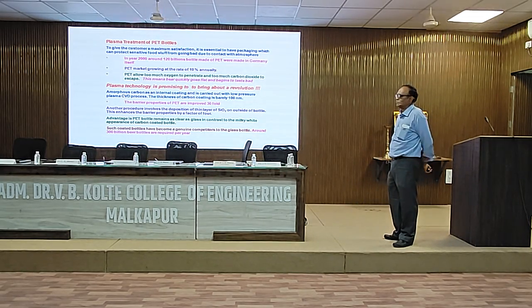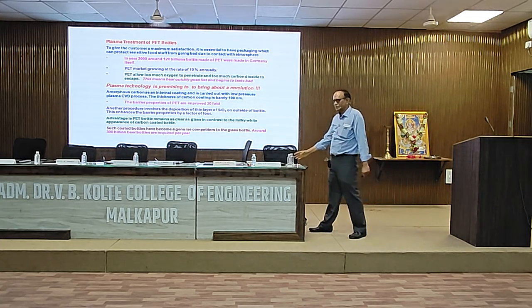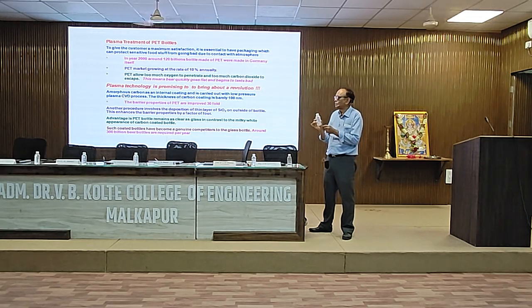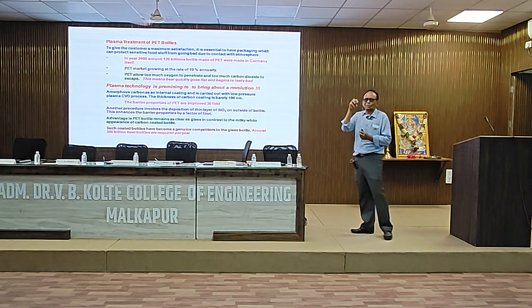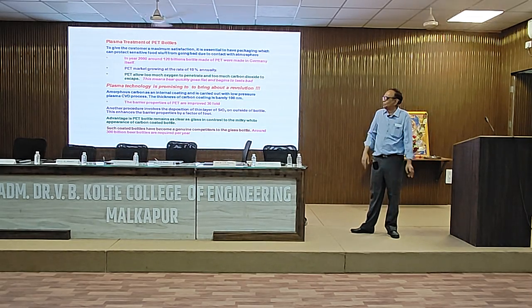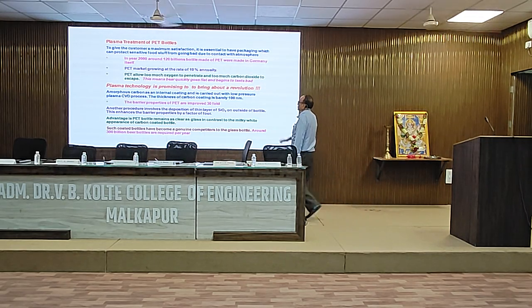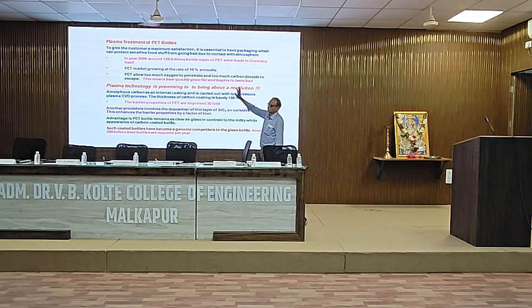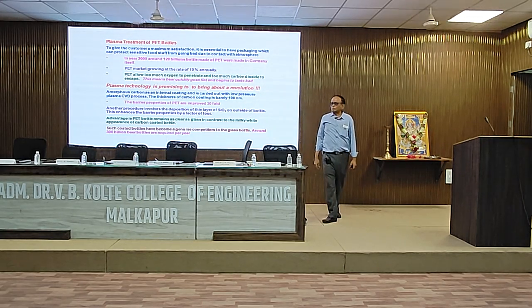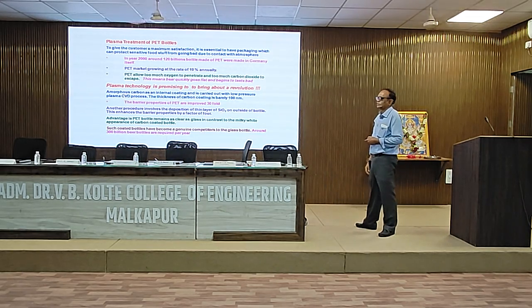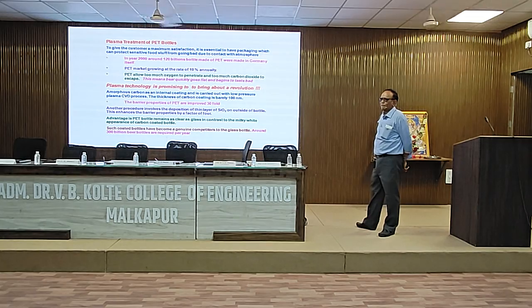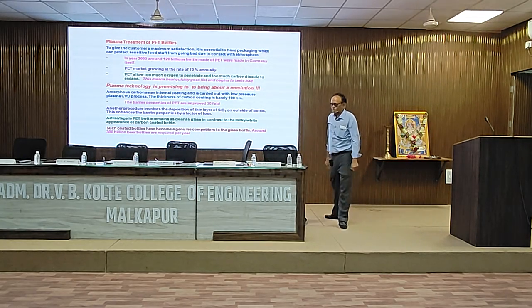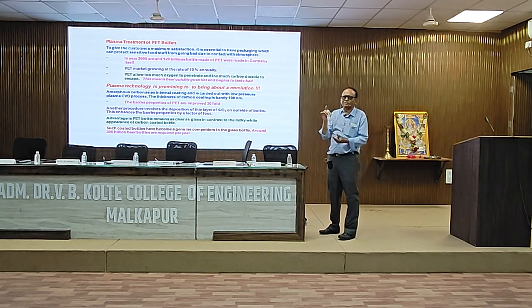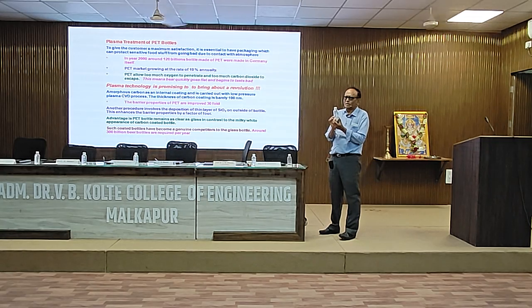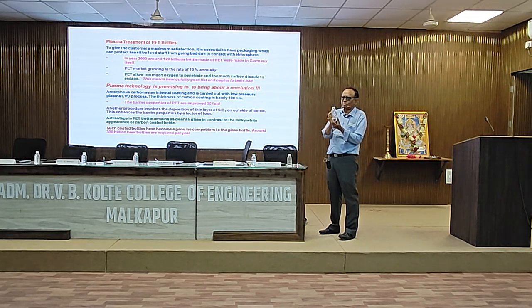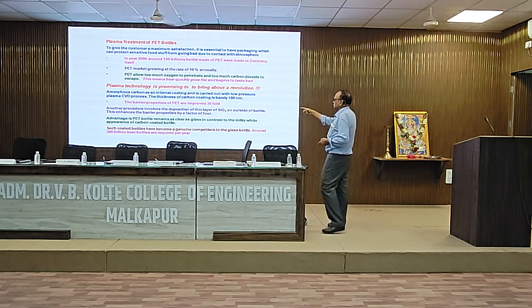The PET market is growing at a rate of 10% annually. But PET allows too much oxygen to penetrate through the pores, and too much carbon dioxide to escape. So if you are storing beer in this plastic container, it will go flat and begin to taste bad. Plasma technology offers a very good solution for this. It brings out a revolution. An amorphous carbon coating on the interior of these bottles can be given by immersing them in the plasma, making the bottle the cathode with a negative bias. You decompose the precursor, and that makes an amorphous carbon coating on the interior, and it is carried out in a low pressure plasma CVD process.